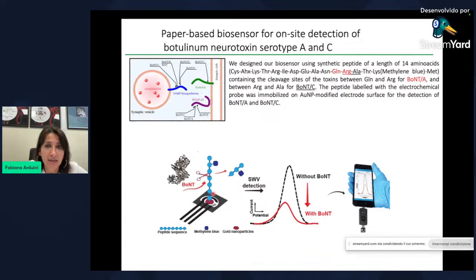We immobilize this synthetic peptide labeled in this part with methylene blue as a redox probe, and this part with a thiol group in order to harness the affinity of thiol with gold nanoparticles. So we print the electrode on office paper. We modify the working electrode surface with gold nanoparticles, and after we immobilize this selected and functionalized